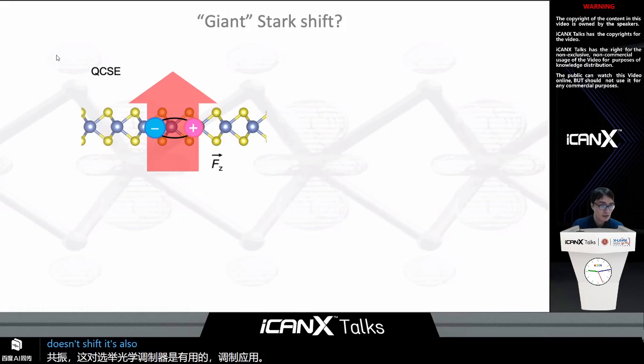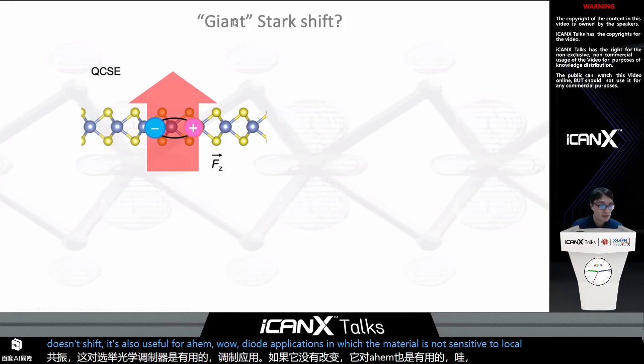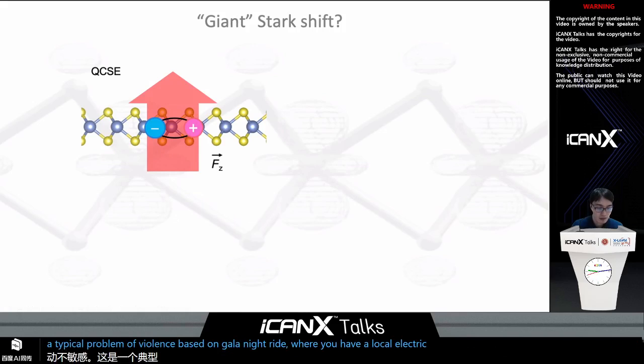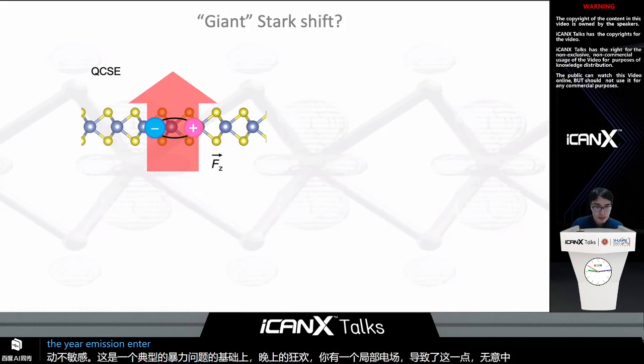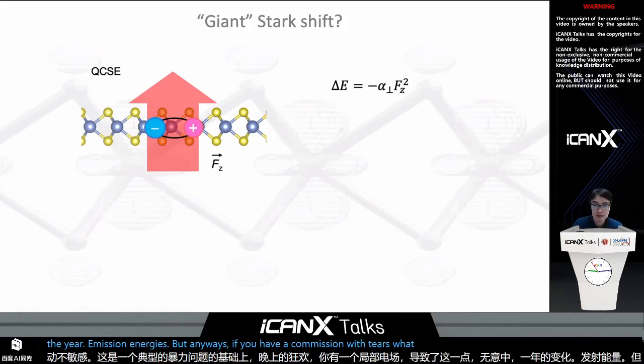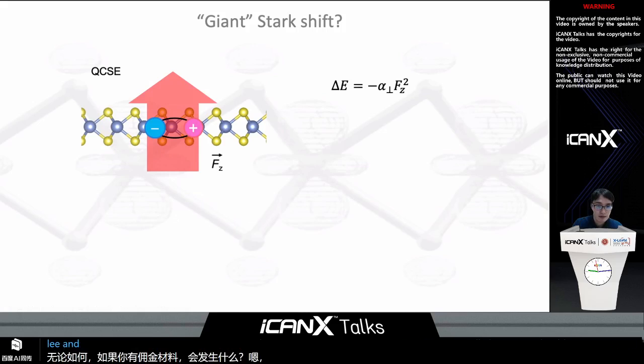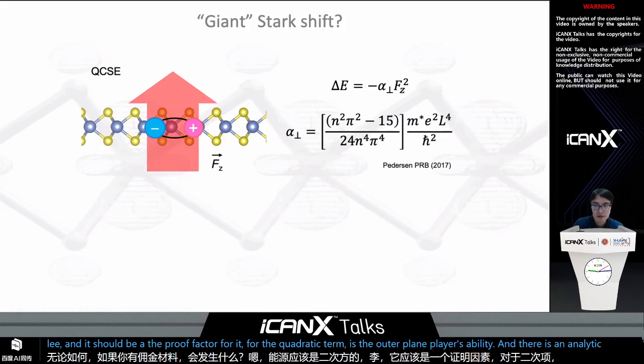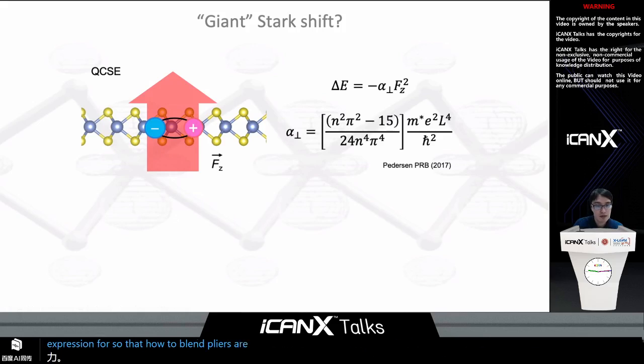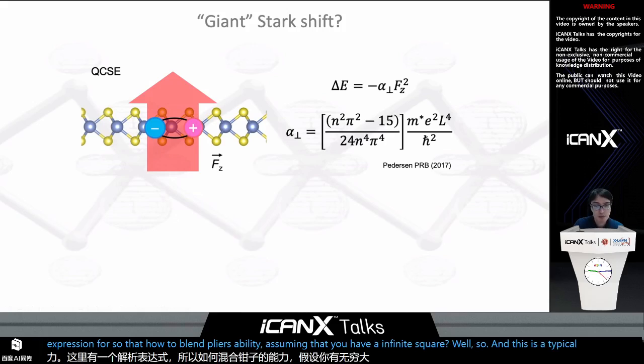If it doesn't shift, it's also useful for diode applications in which the material is not sensitive to local charge fluctuations. This is a typical problem of diodes based on gallium nitride, where you have a local electric field, which causes unintentional shift in the emission energies. But anyways, if you have a two-dimensional material, what happens? Well, the energy should go quadratically, and the prefactor for the quadratic term is the out-of-plane polarizability, and there is an analytical expression for that out-of-plane polarizability, assuming that you have an infinite square well. So this is a typical undergraduate quantum mechanics problem.